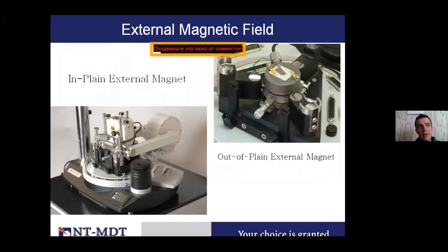Also, many magnetic samples do not show any magnetic properties under ambient conditions. In that case, they require some external magnetic field to show magnetic properties. And in our case, we have the possibility to apply both an in-plane external magnetic field and an out-of-plane external magnetic field. In both cases, you can control the value of the magnetic field from the AFM software. So you choose a value of the magnetic field and measure the magnetic properties together with topography. Then you can change it and measure again, and then you can compare the two images to understand at which value of the magnetic field the magnetic properties change or appear in some structures.